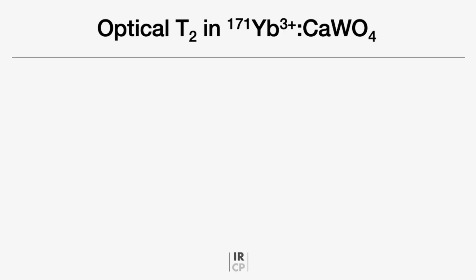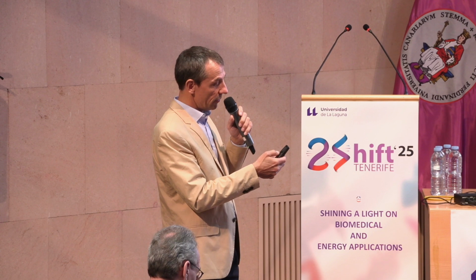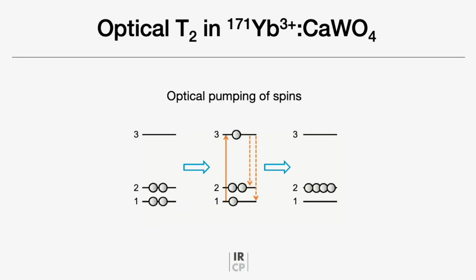And for that, we first use a technique which is called optical pumping of spins. So it's shown here on a very simple scheme. So imagine we start from this situation where we have two spin levels here in the ground state, which are equally populated, and we have the optical excited state. Now we shine a laser on this transition 1, 3.